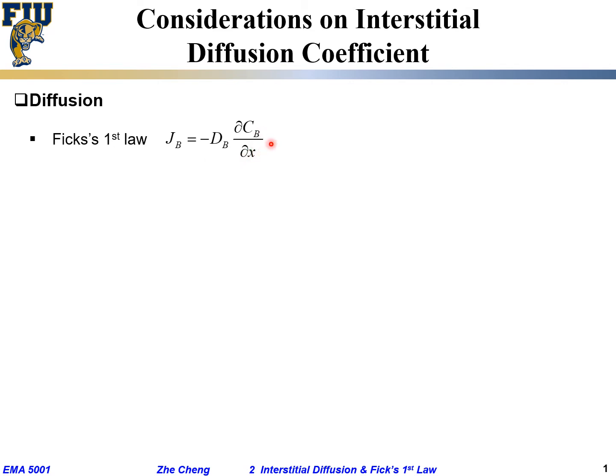Normally DB is a positive number. Which means if along my x direction the partial differential is negative, meaning the concentration is decreasing, then the diffusion is along that positive x direction.